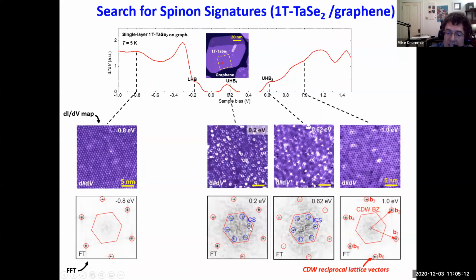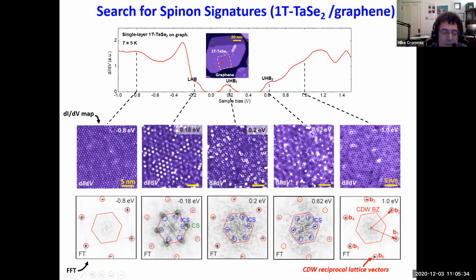And if we go to another energy, this upper Hubbard band 1 here, the lower energy part, again, if we do the Fourier transform, we see those peaks once again. So we see these new peaks. They're long wavelength because they're inside the Brillouin zone. They're much longer wavelength than the CDW peaks. And now let's go to the lower Hubbard band, and we still see the ICS peaks, but now we see some new peaks that are sitting at the K points of the Brillouin zone. We call that CS, commensurate structure, because at those points, the structure is commensurate with the CDW.